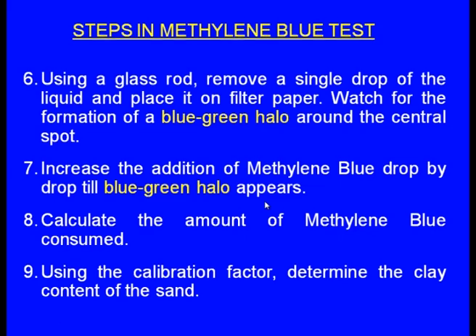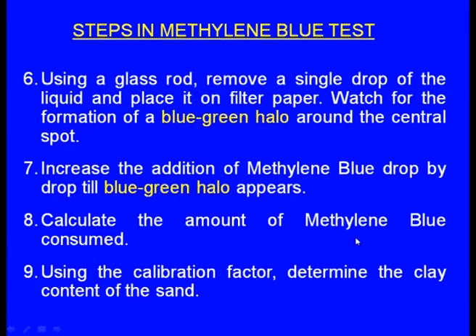Once this blue-green halo appears, we stop dropping the methylene blue solution. We already have the calibration between methylene blue solution and clay content. We calculate the amount of methylene blue consumed from the burette and, based on that consumption and the calibration factor, determine the clay content of the sand. Remember that methylene blue does not react with dead clay — it reacts only with the active clay. That is how we can find out the active clay in the green sand.